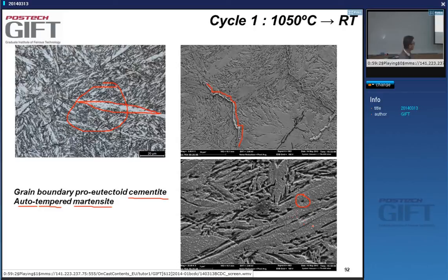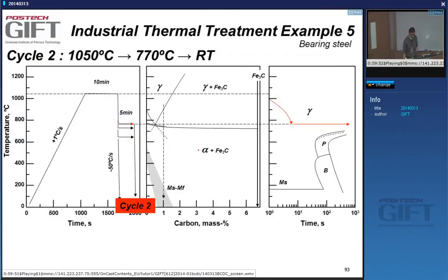Why would something like this happen if you quench so rapidly? Well, when you quench, there is a phase transformation. The austenite changes to martensite. So we already know that there are dimensional changes, expansions. But there's another thing that happens. The heat of transformation is released. During the transformation, there is a heat of transformation that's released, so the material gets warmer. And that causes the material to auto-temper. Heat is enough to get the material to temper the martensite. So that's something that very often happens, this auto-tempering.